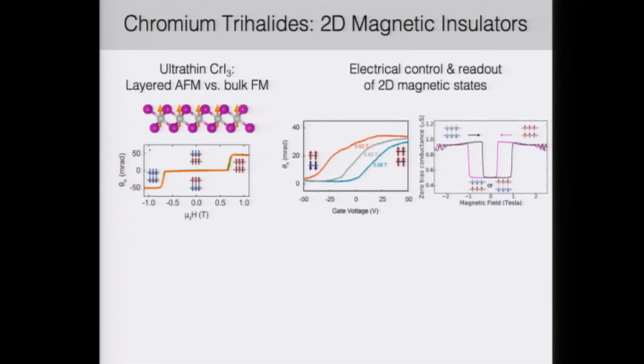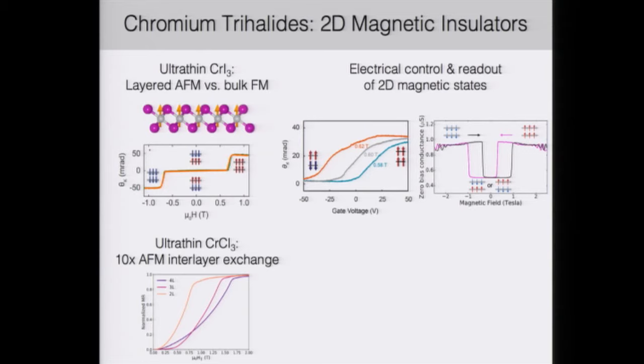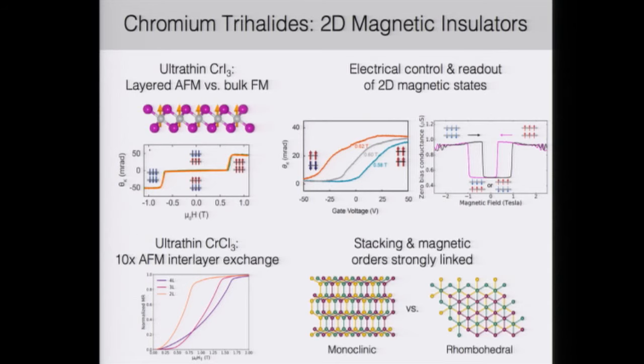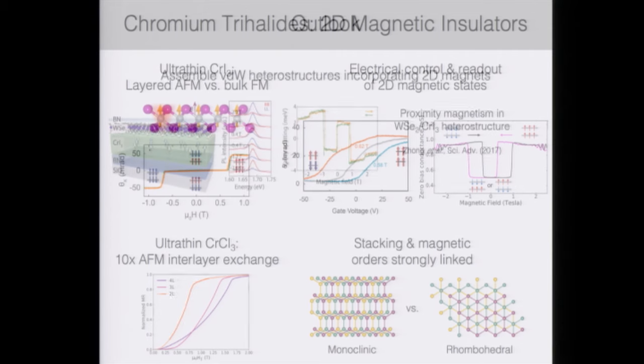And in this system, we've been able to demonstrate both electrical readout and control of the 2D magnetic states in this material. We also have ultra-thin chromium chloride, which has a 10-fold antiferromagnetic interlayer exchange increase compared to the bulk, and which has been very illustrative in showing how stacking and magnetic orders are strongly linked.